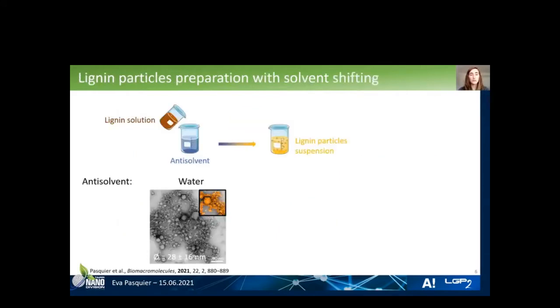So the first thing is to produce the lignin particles. We use a solvent shifting method that is well known. So it consists of dissolving the lignin in a good solvent. Here it's acetone and water. And we pour it into the anti-solvent that is usually water. And by precipitation, it will form some lignin particles.